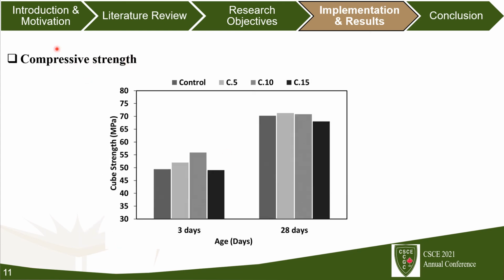And finally, for the compressive strength result, if you look at the early age compressive strength, what was interesting is that when the percentage of limestone increased up to 10%, the compressive strength improved by 13%. However, this improvement in compressive strength vanished after 28 days.